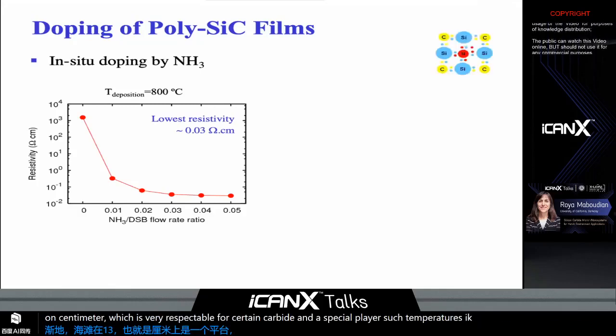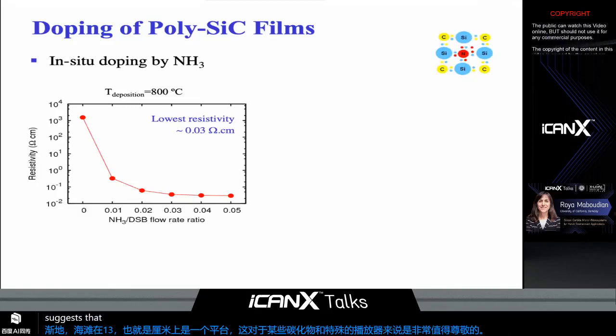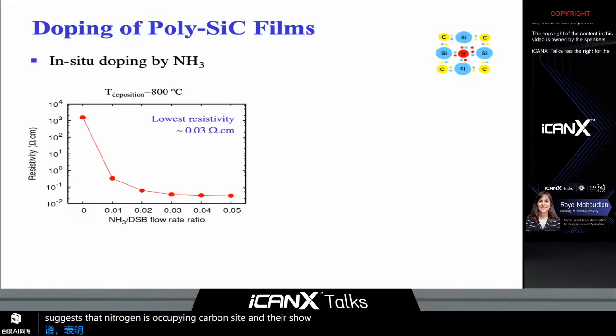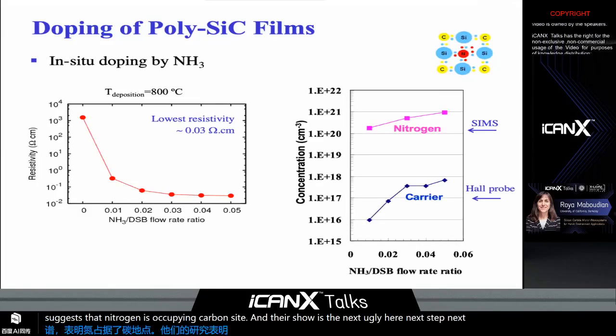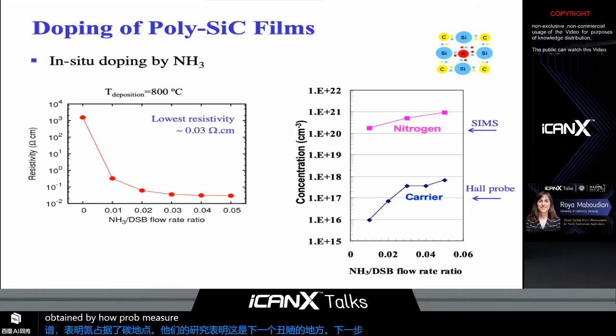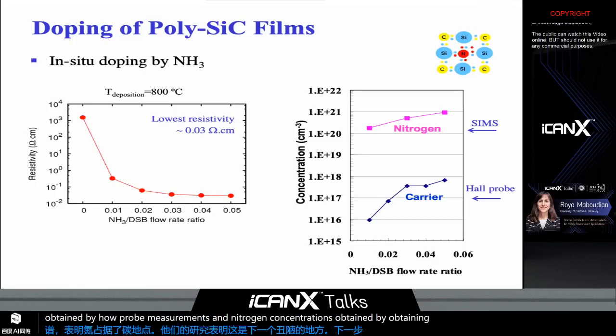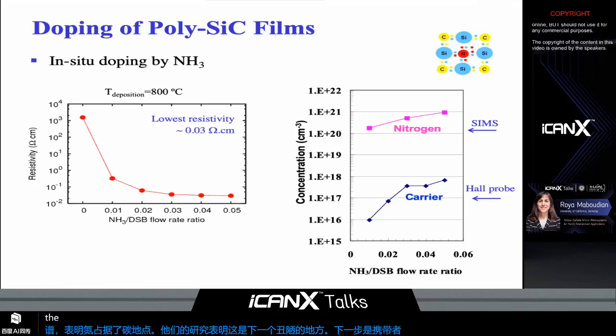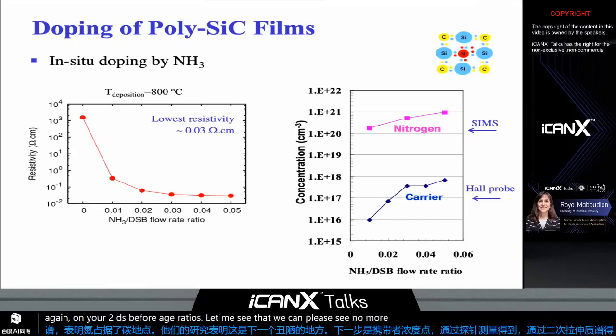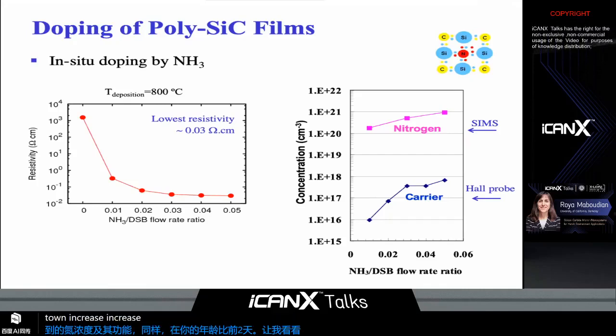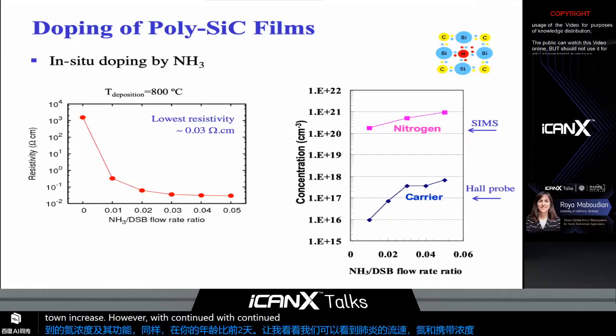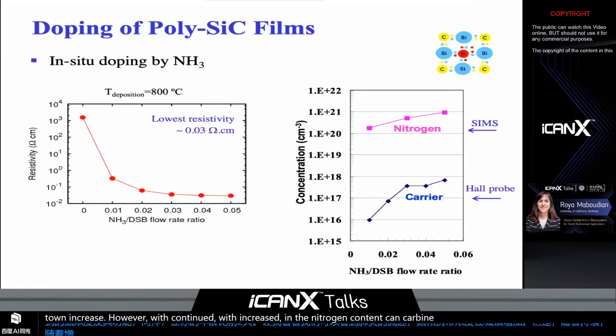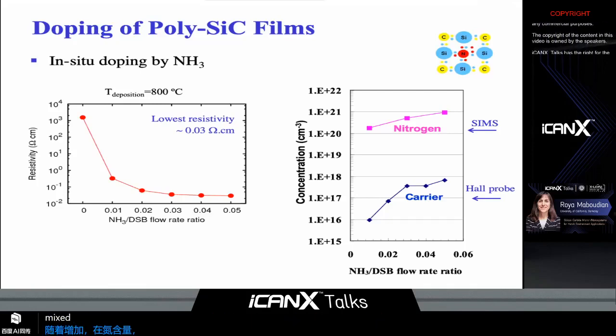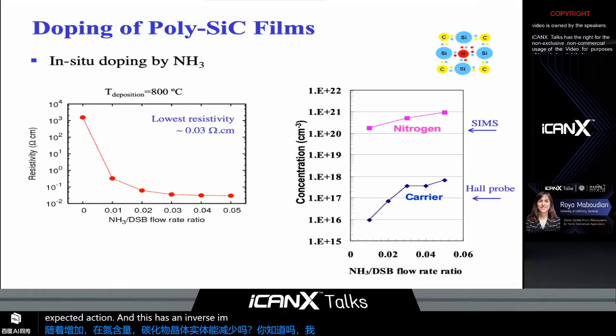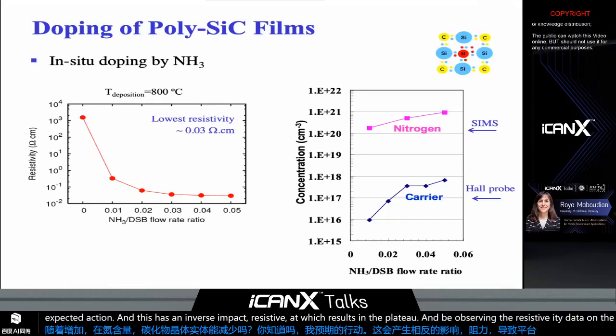X-ray absorption spectroscopy suggests that the nitrogen is occupying the carbon site, as shown schematically here. Next is a plot of carrier concentration obtained by Hall probe measurements and nitrogen concentration obtained by secondary ion mass spectrometry as a function of, again, ammonia to DSB flow rate ratios. What we see is that with increase in ammonia flow rate, nitrogen and carrier concentration in the film increase. However, with increase in nitrogen content, the silicon carbide crystallinity decreases. We know that from X-ray diffraction. And this has an inverse impact on resistivity, which results in the plateau that we observe in the resistivity data on the left-hand side of the slide.